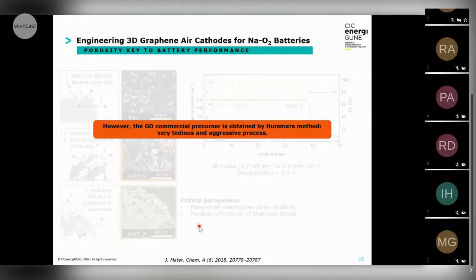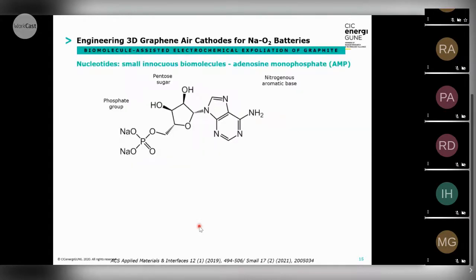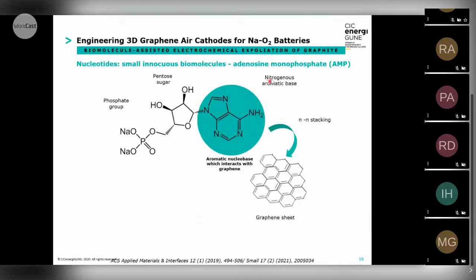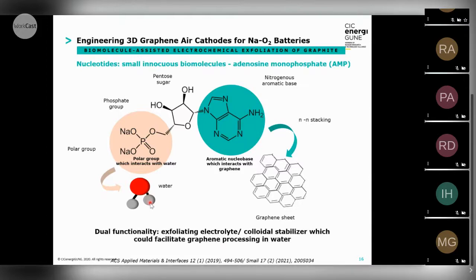So we wanted to go for a more environmentally friendly and more sustainable method. So we explored the electrochemical exfoliation of graphite using nucleotides. These nucleotides, adenosine monophosphate, are really nice because you have an aromatic nucleobase which interacts with graphene through pi-pi stacking, and also a phosphate group which is polar and can interact with water. Remember that I said before that the problem of the electrochemical exfoliation was not having a good dispersion, because the water does not interact with the graphite, and we need surfactants. In this case, with a nucleotide, we can have this great interaction. So we have a dual functionality: we exfoliate the electrolyte, and we have a colloidal stabilizer, which facilitates the graphene processing in water.